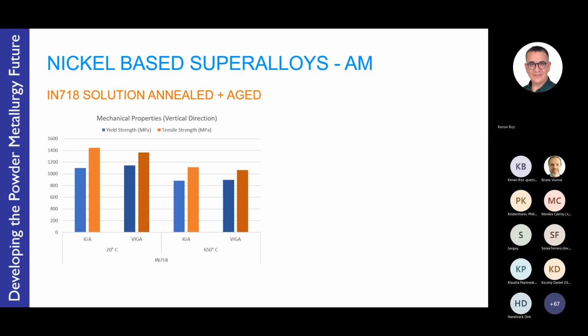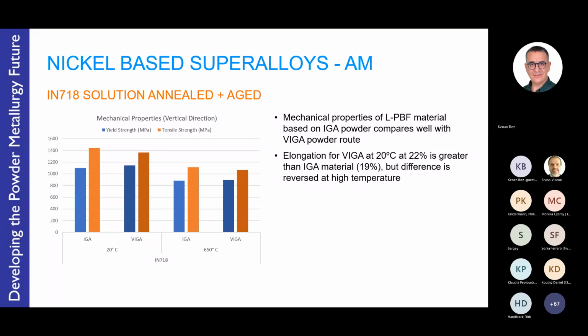Here, presenting some properties comparing inert gas atomized Inconel 718, which is a slightly lower cost process compared to vacuum inert gas atomizing, especially from a capital equipment point of view. And here you can see the properties of mechanical strength in the vertical direction for yield strength and tensile strength, both at ambient 20 degrees and 650 degrees C.